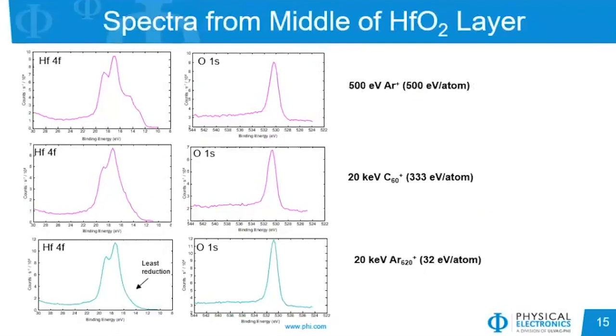And the plots from top to bottom are the monoatomic argon, the 20 keV C60, and the 20 keV argon 620. As we have shown before, under monoatomic argon, we do see reduction of the hafnium going from a fully oxidized state to a reduced state, as you can see by the broadening of that structure. We do see actually the least reduction from the 20 keV argon 620, which is in line with what we have seen from eV per atom considerations previously shown.